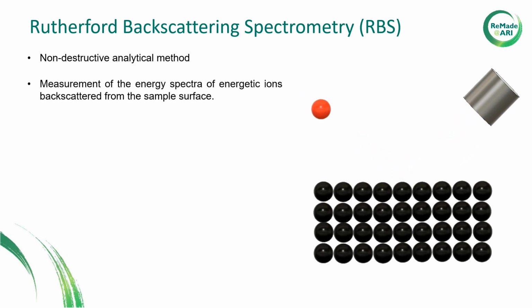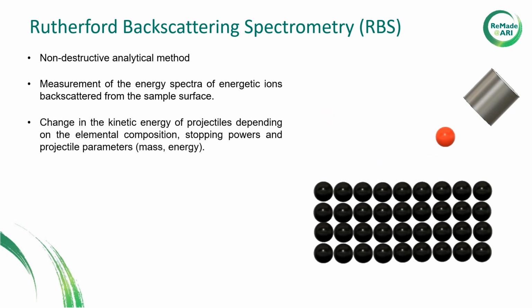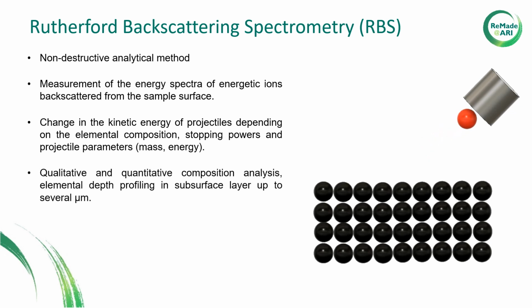The principle of the method is the bombardment of the sample with energetic light ions, which are backscattered from the surface atoms towards the detector. During the collision, projectiles partially lose their kinetic energy depending on the energy stopping powers, the elemental composition of the sample and projectile parameters, energy and mass. The outcome of the measurement is the energy spectrum of energetic ions, which is then used for qualitative and quantitative composition analysis, as well as for elemental depth profiling in the subsurface layer up to several micrometers.